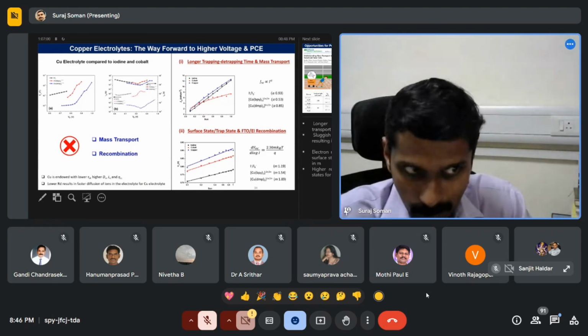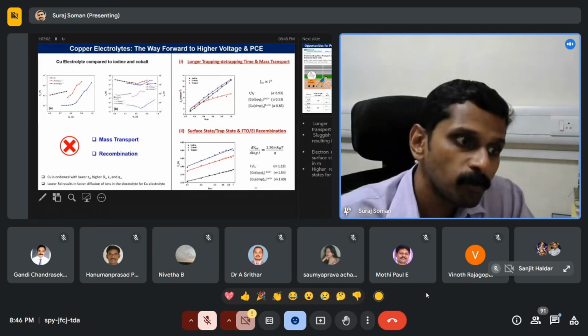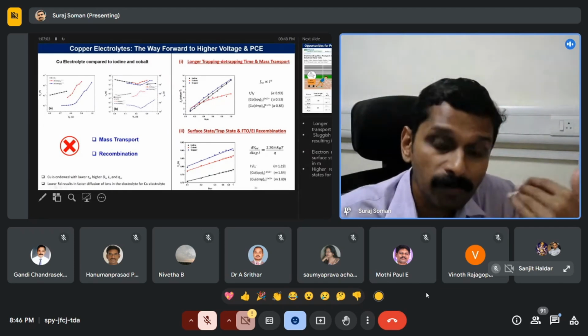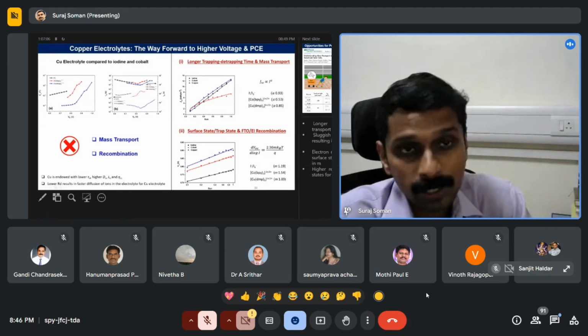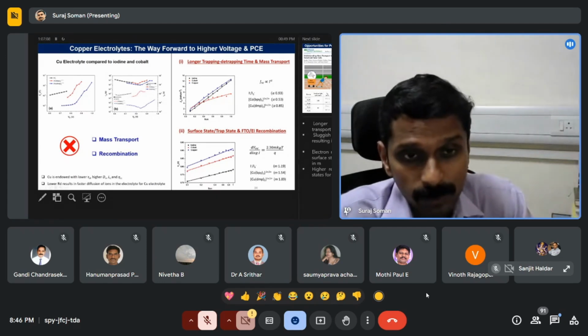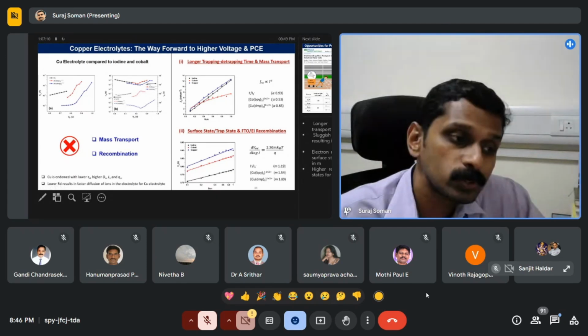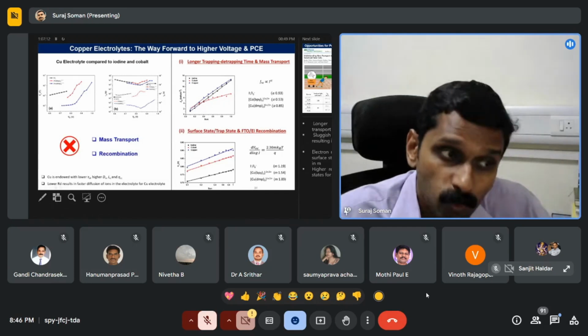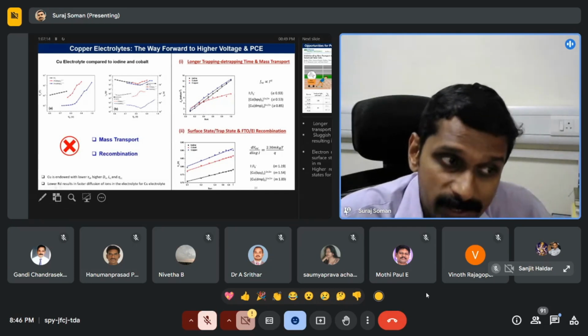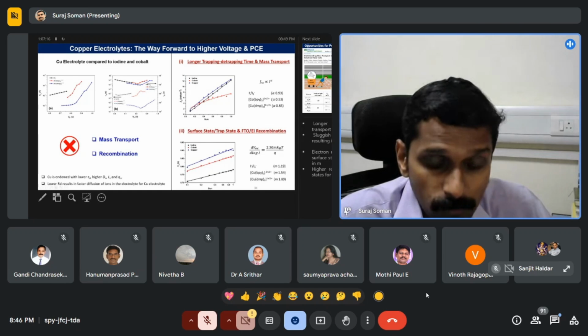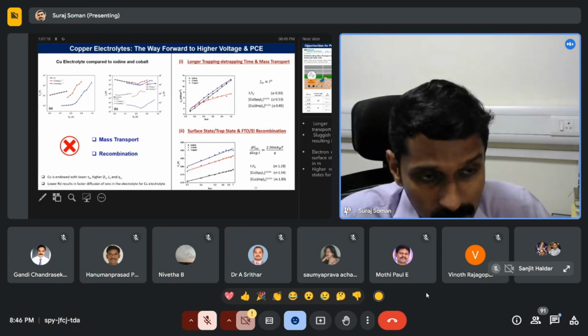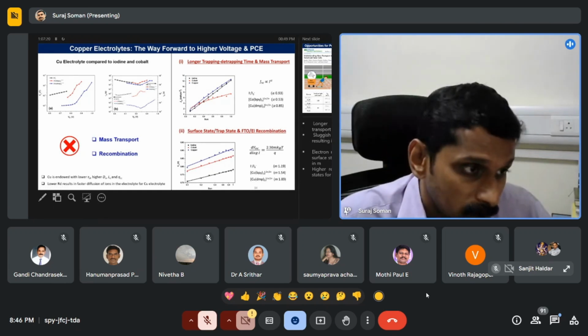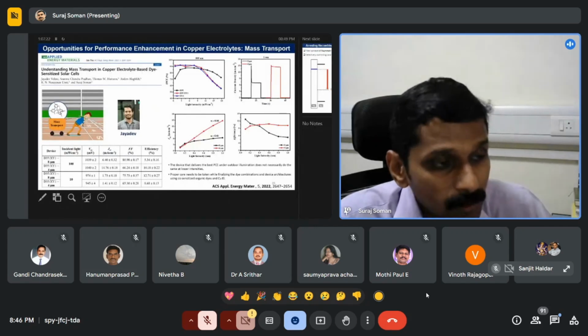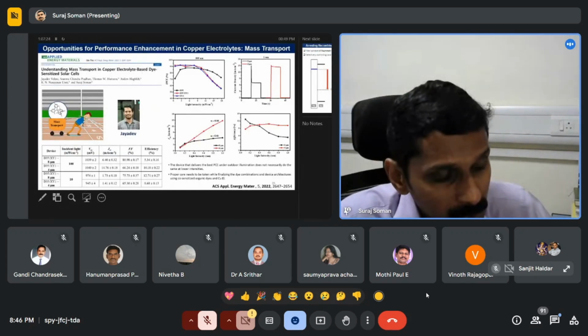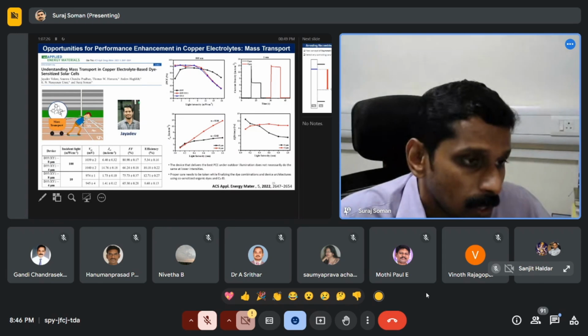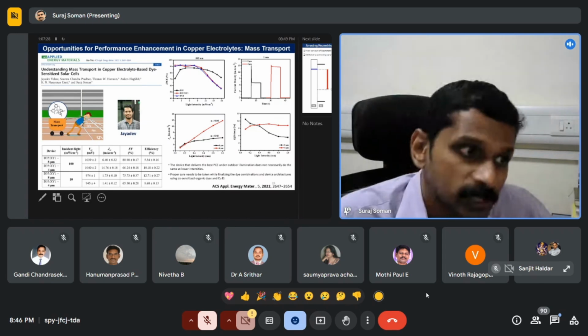What's next? There we went deeper and did some trapping, detrapping measurements, and we found that there are two critical issues still there for copper. One is the mass transport and the second is the recombination. If you can address these two problems, then you can further improve the performance of these devices. One of my other students, Jaydev, came up with a very interesting study where we addressed one problem, which is the mass transport.